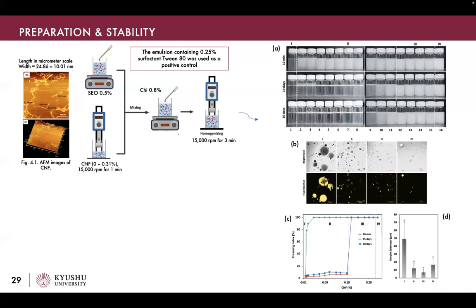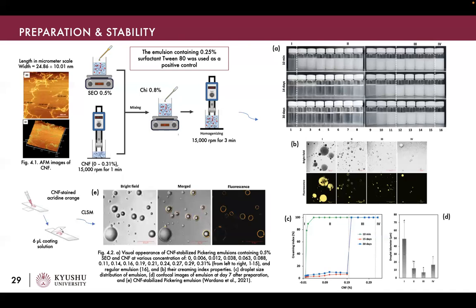And to further understand the structure of Pickering emulsion, the acridine orange fluorescence dye was used. The orange circles around the spherical droplets indicated that the stained cellulose lay on the surface of the dispersed phase.